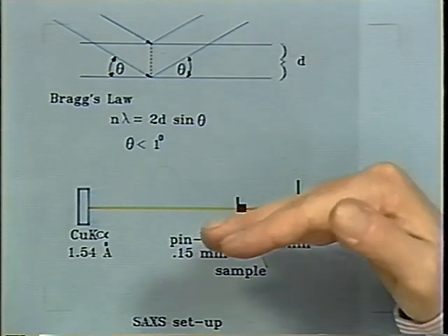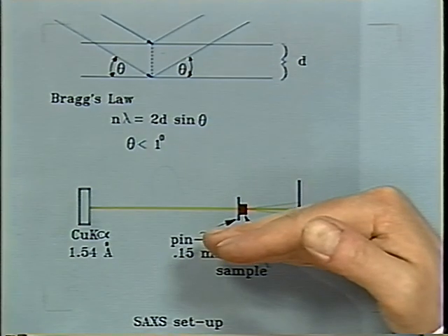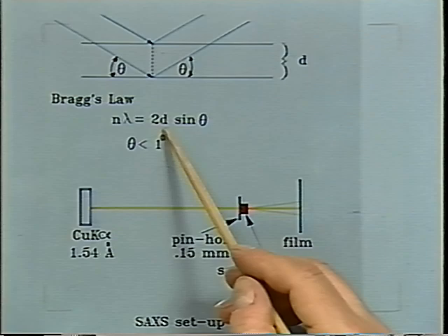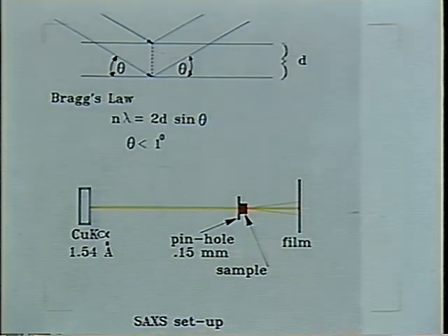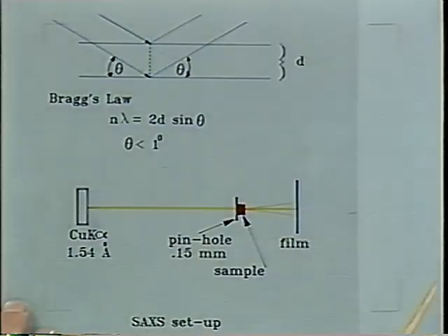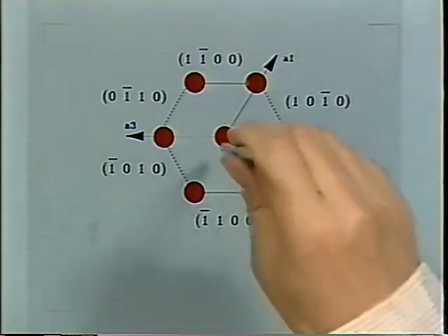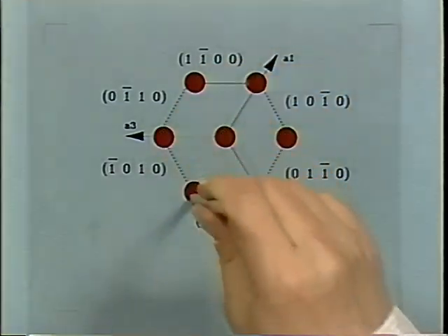So the pattern on the film will only be there if we get order. If we have order in the structure in the direction of that light beam, that's very nice. If you would have a smaller value here, then you would get some scattering even at larger deviations from here. So you will see the patterns from that structure are very regular because of that spacing. It's just right. Now, when looking at scattering from regular structures, here you see an example, cylinders being on the hexagonal pattern.